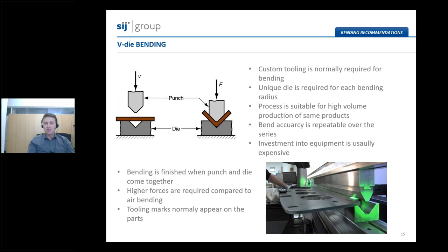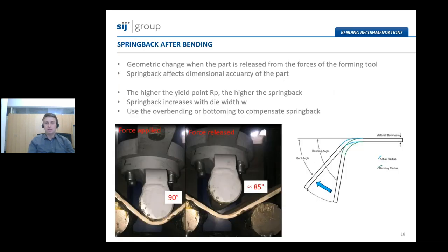And this type of bending is normally not practiced on plates with relatively low thicknesses. So mostly we can use the V-die bending on SIMAXX and SIDUR grades with a thickness between 6 to 12 millimeters. So let's check the spring back effect.